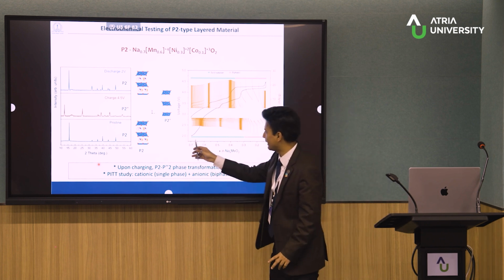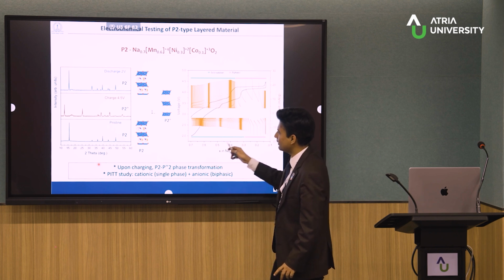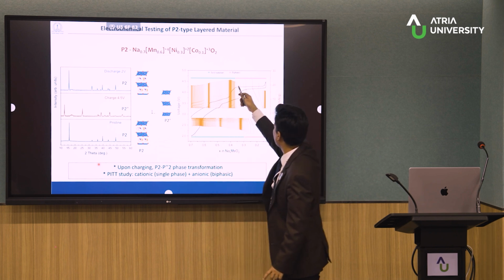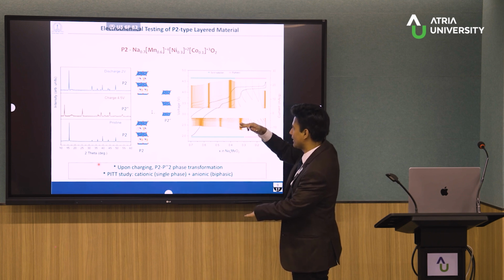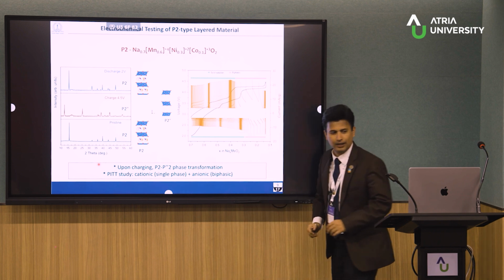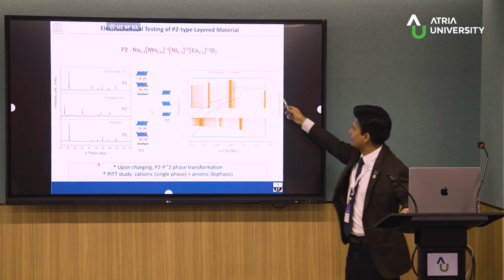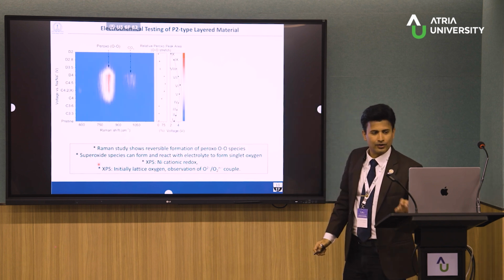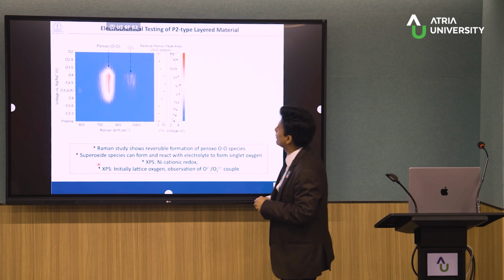So in principle again, throughout this process up to this, the P2 structure remains intact, and here it becomes O2, with a sudden change in expansion, again comes back and so on. So the anionic redox here, we wanted to probe further. So we did some in situ Raman spectroscopy.